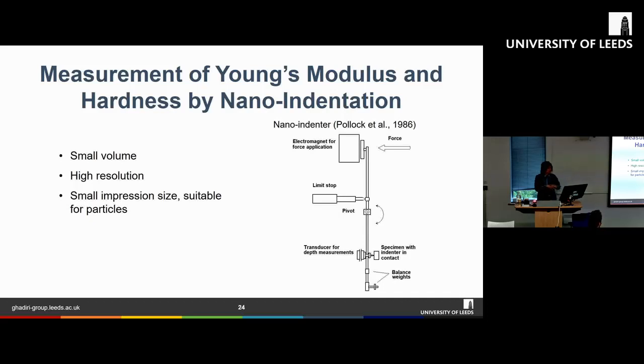Right. So I mentioned that hardness is normally measured by indentation. But the previous indenters that I was talking about are mainly for bigger samples. In powder characterization, we're interested in the mechanical properties of single particles. Sometimes we're talking about maybe 100 microns, or in some cases even less than that. With the types of indenters that I showed earlier, it can prove quite difficult to prepare the sample and also to indent it, because the indenters are bigger compared to the particle size.